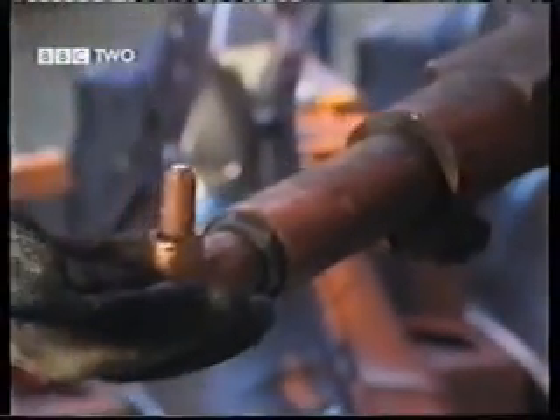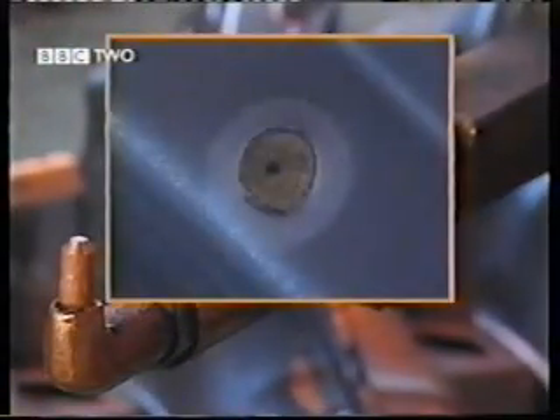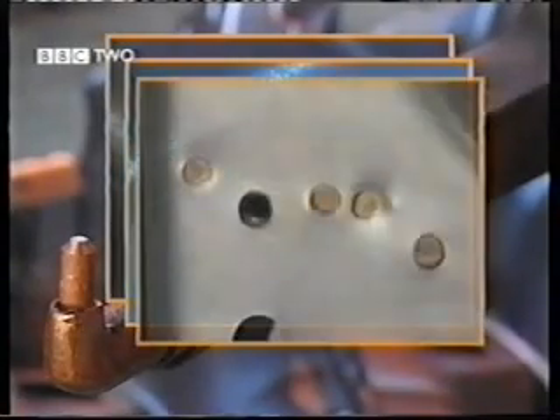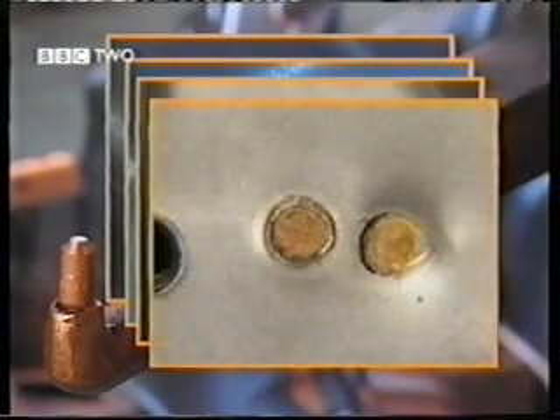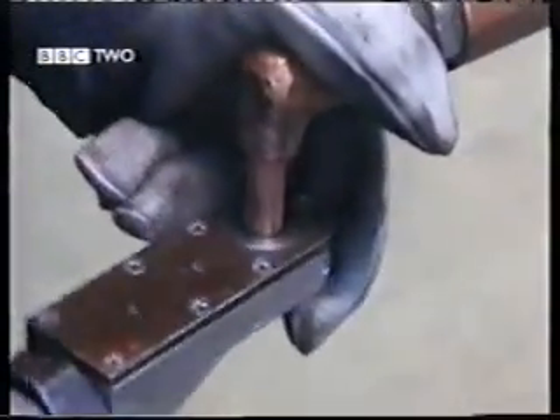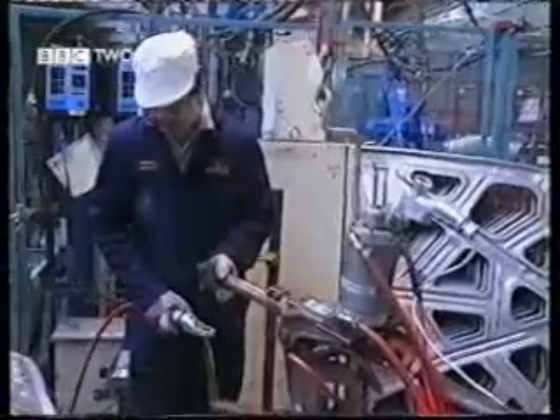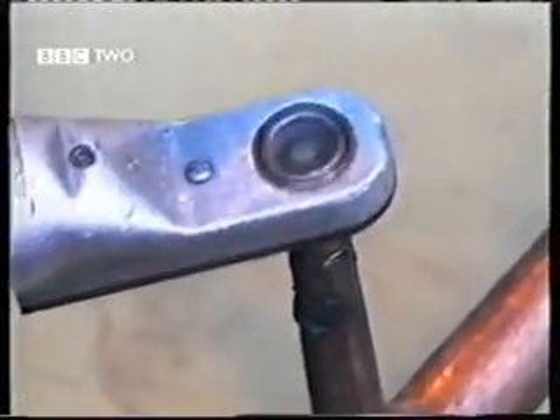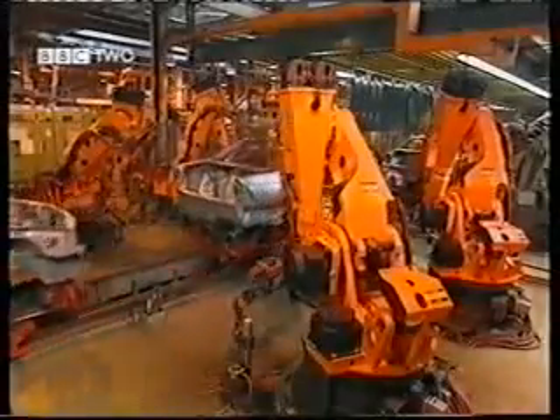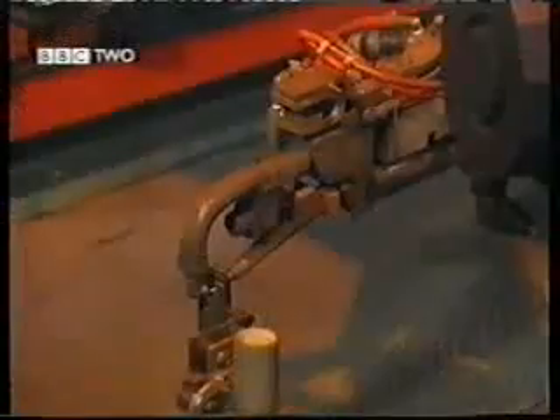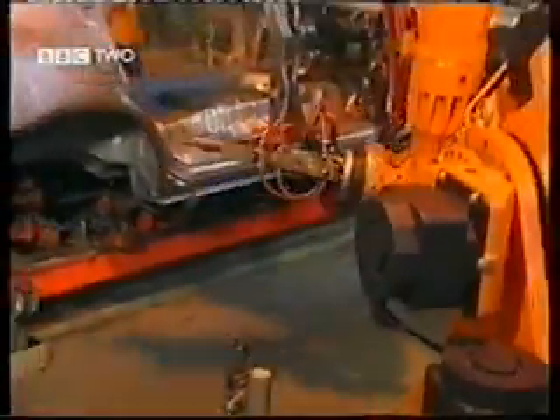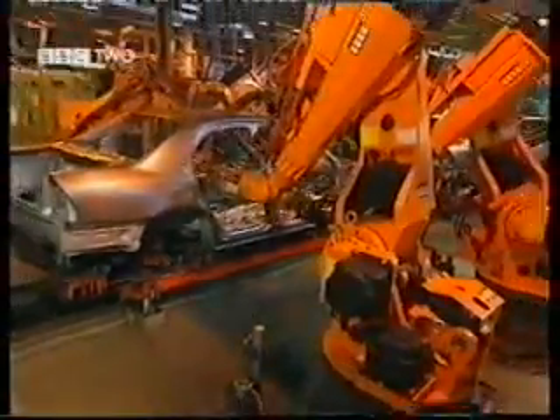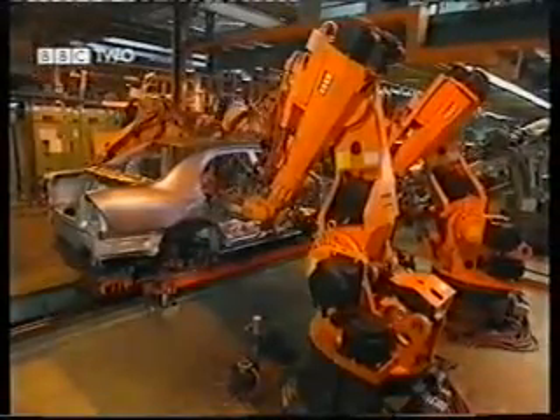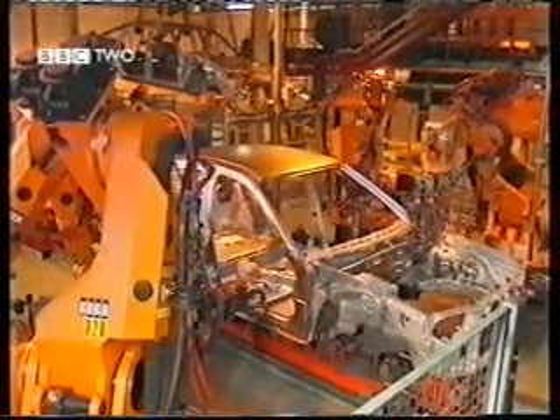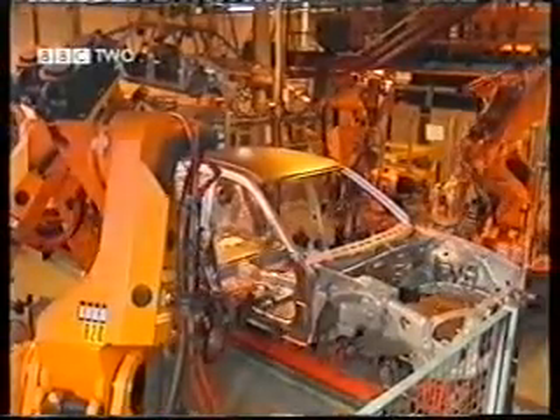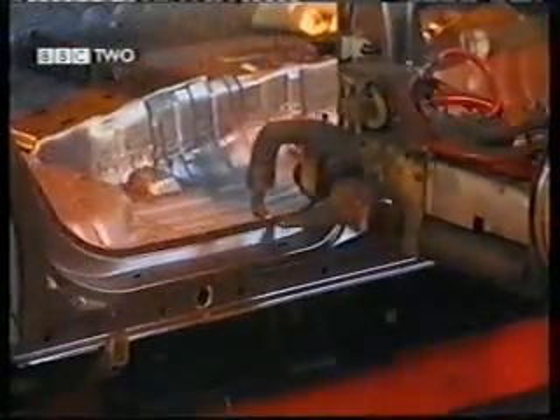Molten zinc reacts with copper in the electrode, forming brass, which you can see in these spot welds quite easily. It also affects the electrodes, which have to be redressed frequently to maintain the correct current density at the tip. Ensuring welding efficiency has been a major achievement here on Rover's assembly line at Cowley.